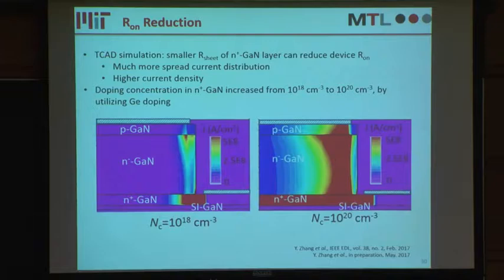So we increased the doping level in this layer of our wafer from 10 to the 18 to 10 to the 20. However, even with a doping level as high as 10 to the 20, the current distribution is still not completely uniform. This is limited by the quasi-vertical structure.